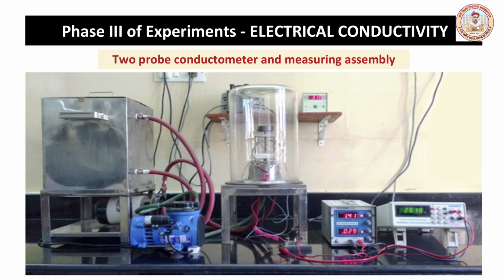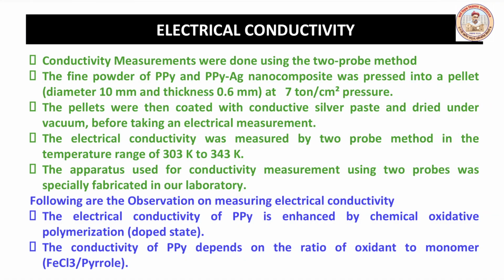Now we have to check, since it is a conductive polymer, what is the conductivity obtained of the samples. The picture here is of the two-probe conductivity meter used for conducting measurements of the samples. Conductivity measurements were done using the two-probe method. The fine powder of polypyrrole and polypyrrole silver nanocomposite was pressed into pellets at 7 ton per centimeter pressure. The pellets were then coated with conductive silver paste and dried under vacuum before taking an electrical measurement.